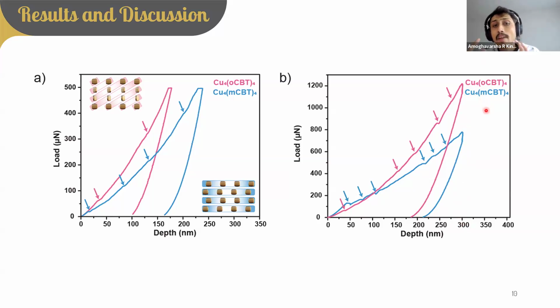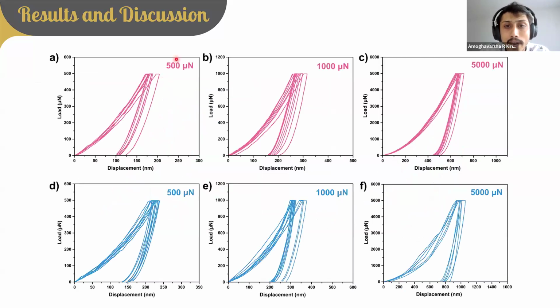Now, we cannot arrive at this conclusion from a single measurement. So we did multiple measurements at multiple different forces or pressures applied onto the sample, and also multiple different load functions. The load function is the time we give for loading, holding, and then unloading of the indenter tip into the sample. We did this at 500, 1000 and 5000 micronewtons of force, and we can see that all the data converge to points very near to each other. That means the data are repeatable.